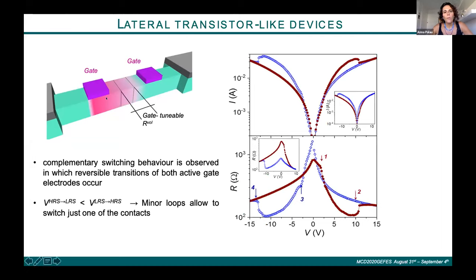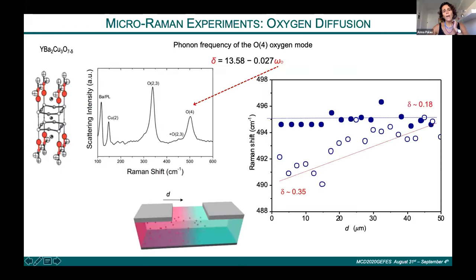We have also performed lateral oxygen motion, to see if we can move the oxygen not just below the gate, but from one gate to the other. These are the hysteresis loops that we obtain, which show a complementary switch between one gate and the other. One gate switches to the low resistance state while the other switches to the high, and the contrary when we apply the other polarity. By doing this complementary switching in the two gates, we are able to induce a gradient of oxygen between one gate and the other.